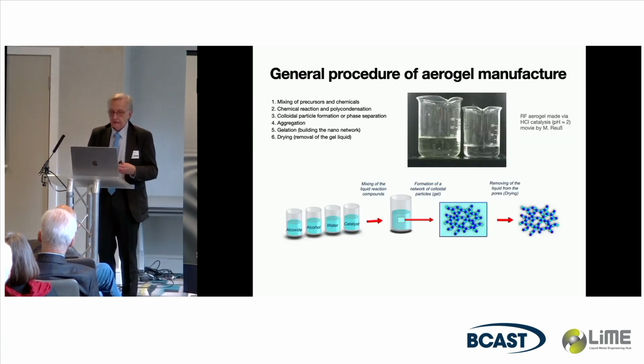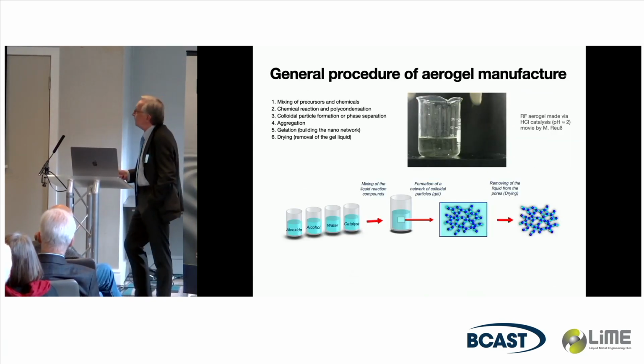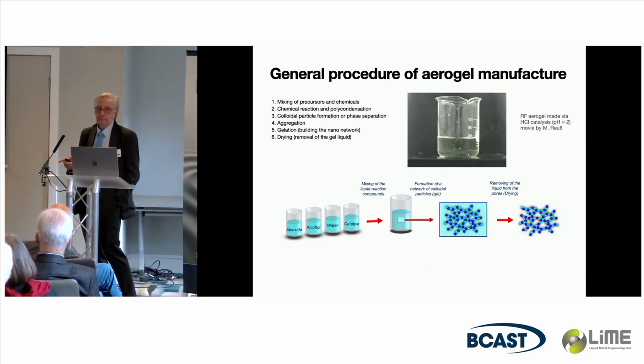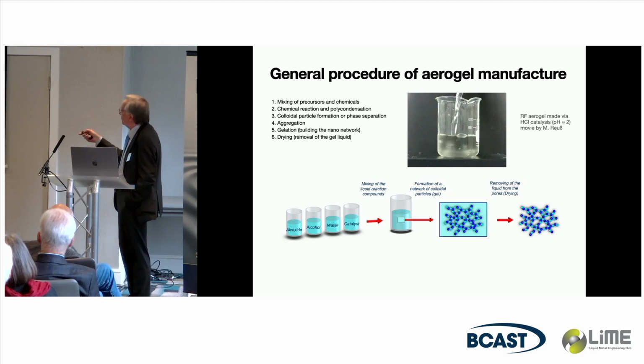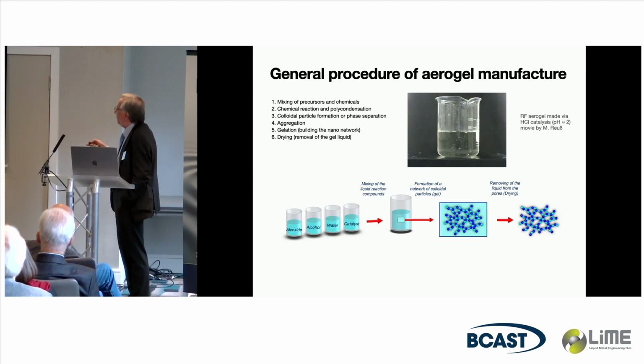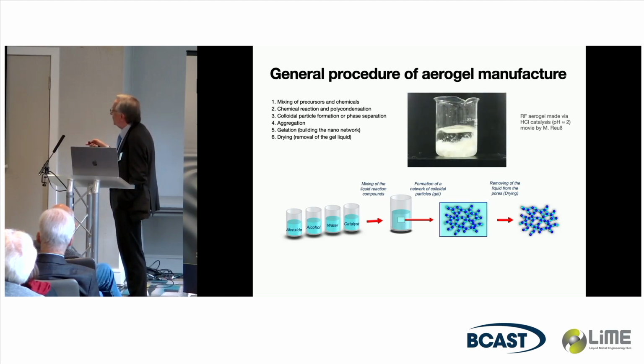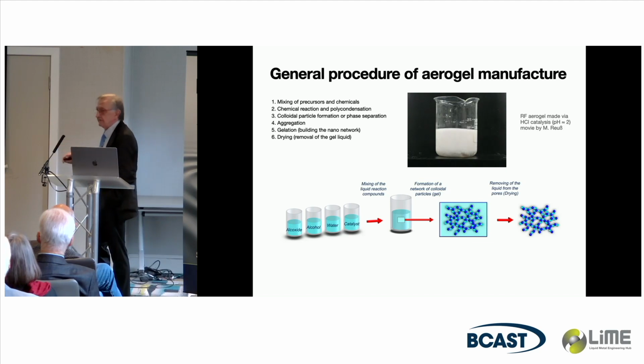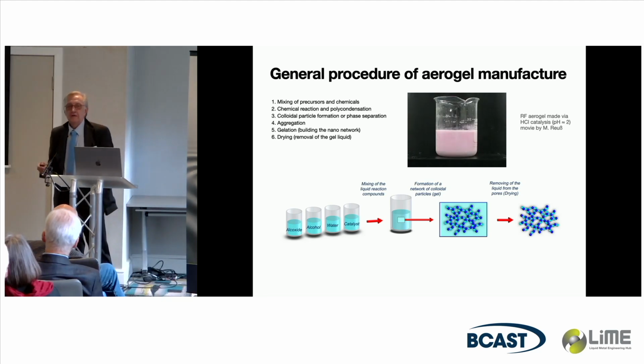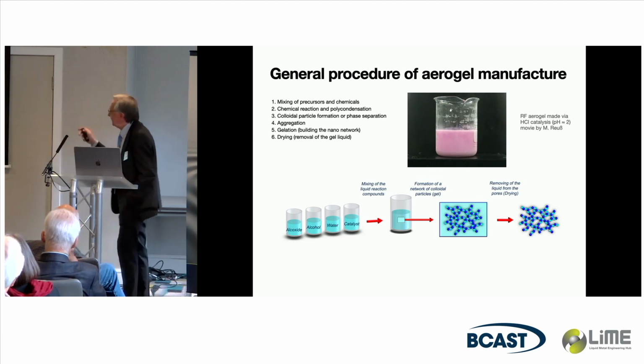Now you see how one really does it. That's a real experiment in real time. One of my postdocs mixed resorcinol in water solution and then added formaldehyde with a catalyst. Shakes it a little bit. You see a lot of particles appear. It was clear, now it's turbid, and now it's got pinkish, and it's gelled already. This is real time, but typically gel time in aerogels is hours, 2 days. But this is fast.